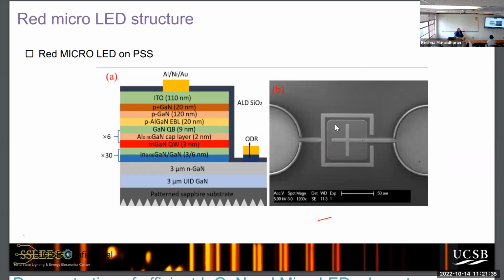Okay. So I mentioned there was one other problem we had to solve, and that is to get red on the same wafer. So in the red, believe it or not, the only thing we had to change was the quantum well material from blue and green to red. So that means putting more indium in. But we also had to add a very high aluminum cap on top of that to keep the indium inside from diffusing out. So we did a slight change there in the epitaxial layer stack. And this is all grown within, it takes only about 2 hours to grow this entire stack, but it takes a month to fabricate the device. So the fab's hard. The stack is actually the easy part.